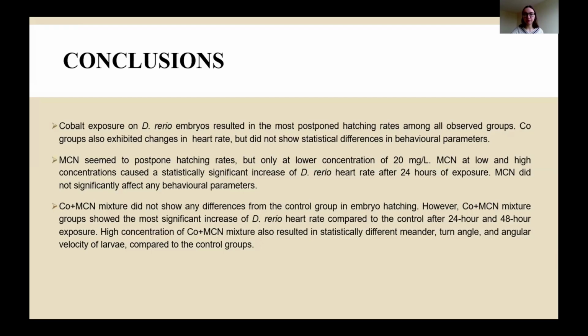And finally, the cobalt plus MCN mixture did not show any differences from the control group in embryo hatching. However, cobalt plus MCN mixture groups showed the most significant increase of Danio heart rate compared to the control after 24 and 48-hour exposure, but again, no differences were visible after 72-hour exposure. And finally, a high concentration of the cobalt plus MCN mixture also resulted in statistically different meander, turn angle, and angular velocity of larvae compared to the control groups. So to sum up everything, cobalt plus MCN seems to have some effects on Danio, but they do not seem to have acute toxicity. However, to answer more for sure, more experiments should be conducted in this area.